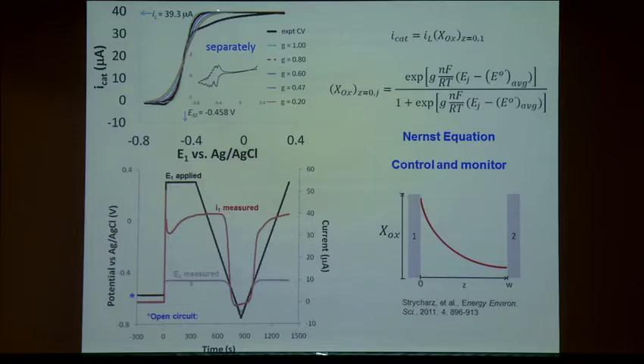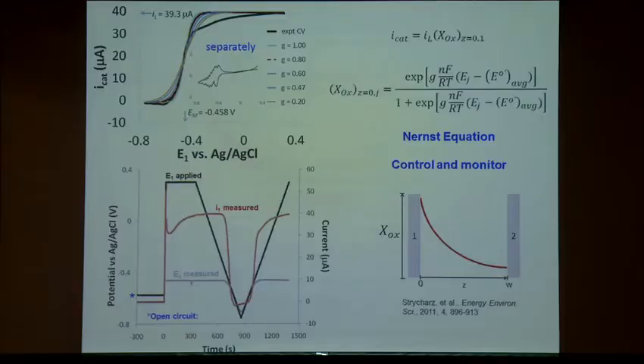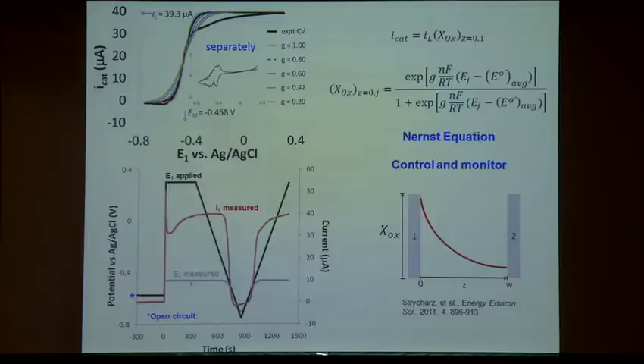And the key thing is this is a derivative of the Nernst equation, where we included this term G. This is a pretty messy voltammogram, and what it indicates is probably an overlap of a number of different cytochromes or charge transfer mediators. The inclusion of G essentially allows me to determine the voltammetric window I need to go from fully oxidized to fully reduced. As I make this number smaller than 1, the voltage range needed to go from fully oxidized to fully reduced cytochromes at the electrode surface is wider. And so we can fit this curve. A good curve is G equals 0.8, which says that there's some heterogeneity of the charge transfer mediators involved in the electron transfer process.